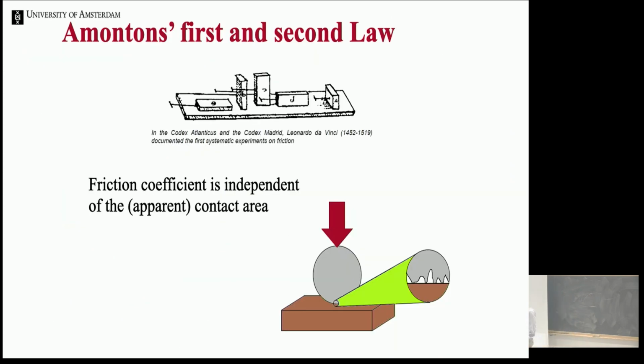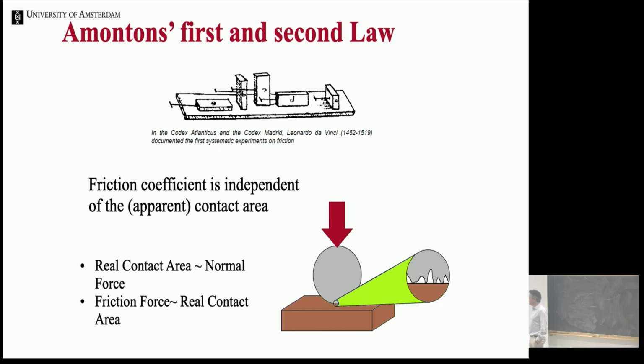Okay, and so to really understand that, we really need to think a bit deeper about friction. And I told you yesterday that Da Vinci did experiments where he had wooden blocks and a wooden plate, and he concluded that it didn't matter whether he put the block on the side or on its flat face, that the friction coefficient was always the same. And so the friction coefficient that Da Vinci measured and that many engineers measure every day seems to be independent of the macroscopic contact area between the two surfaces. And that seems a very strange observation, but not if you realize that all surfaces are rough.